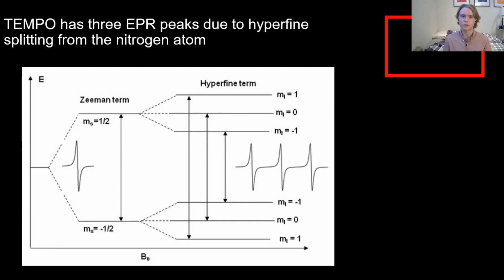So if we look at this image, we see we have our Zeeman term, which is the term that I was talking about earlier with our single electron. We have our negative 1/2 spin and our positive 1/2 spin that are being split in energy by our magnetic field, and that would give us our single peak. Now, if we introduce our nitrogen, it actually has 3 different spin orientations, either -1, 0, or 1. And what we see here is that each of these three states splits each of the two states for the electron into three states. So we end up getting 6 total states here.